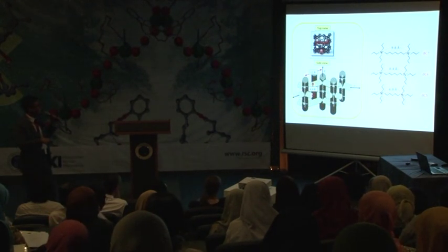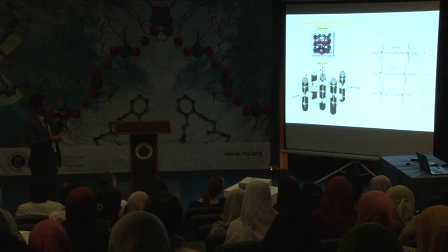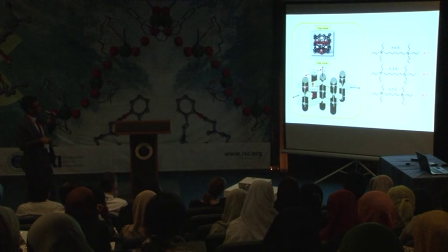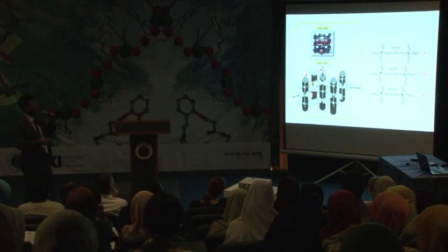We look at the channel within the MFI zeolite, for instance. If you look at this top view, you can put a balloon. This was taken from the Denmark University. So you can put the balloon in the unit cell of the MFI framework. You can have a straight channel and a sinusoidal channel. This is a typical characteristic of the pore in the MFI zeolite. And if we look at this channel in this image, the side view, actually this channel was developed by organic molecules. That's what we call structure directing agent.